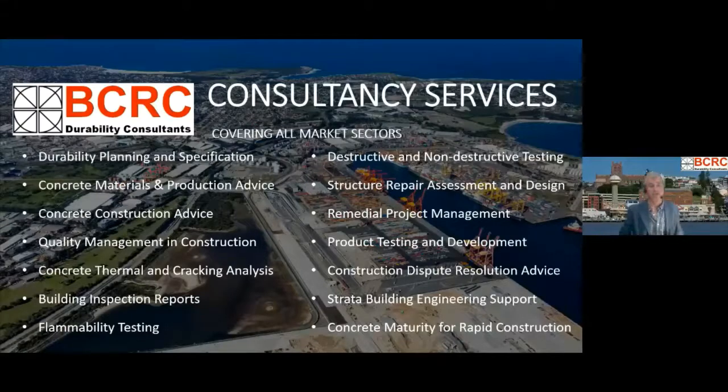Well, absolutely. I guess you don't have the accelerated carbonation in those structures, I assume, but certainly we have seen it in underground tunnel structures and in culvert structures. Those are two that I can remember us dealing with in the recent past. Exactly these problems occur. So if you're in a contaminated groundwater situation, then any concrete structure that is below the water table is going to have these sorts of problems, and you have to really look carefully at the design and at the execution. I think it's important to note that if you're using precast elements, then they can be manufactured to a higher standard, and the jointing is the critical issue there, but the concrete itself can be produced to a higher standard with greater care taken in producing the elements that might go into a structure that's below the water table.